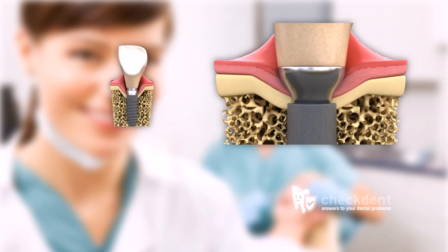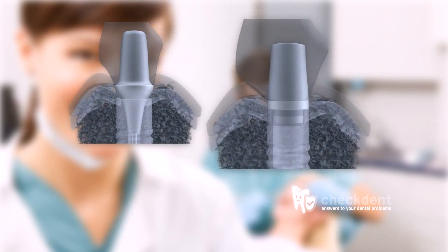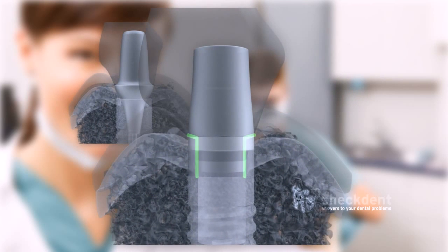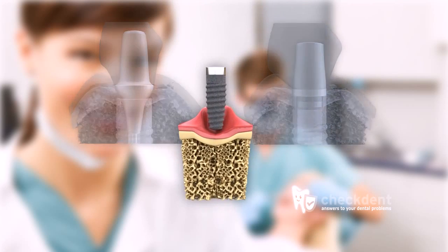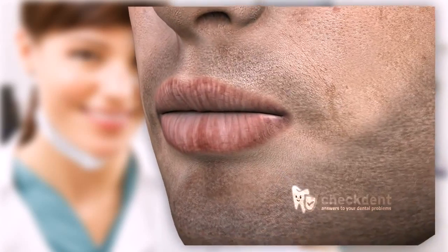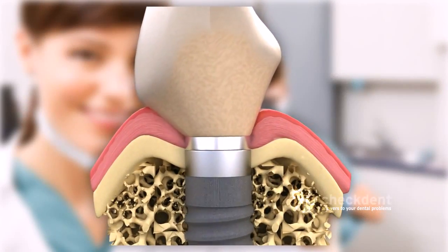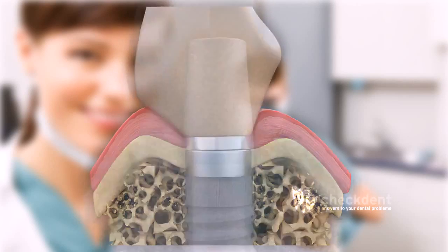Today, we know why there is bone loss with plug-in connections. With conical connections, abutments and implants are linked so tightly that not even a scanning electron microscope can reveal any spaces or gaps. Conventional plug-in connections provide a less than optimal implant-abutment interface, leading to a clearly visible gap. Immediately after insertion of the abutment and crown, this gap gets occupied by bacteria and bacterial products, and chewing motions cause movement between the implant and the abutment, creating a pumping effect. This movement is clearly visible in the special images.